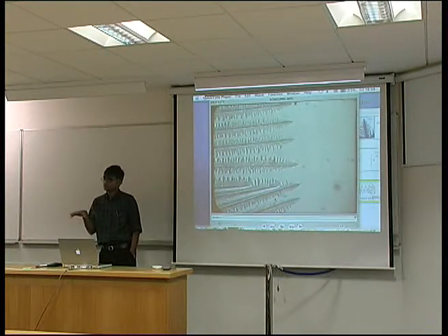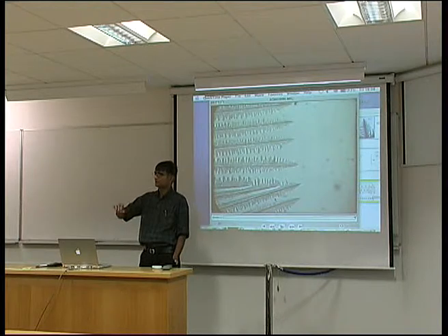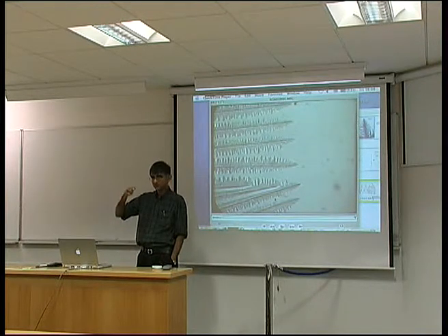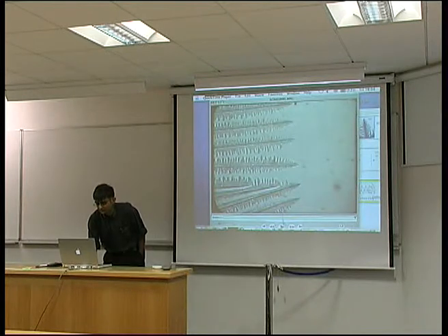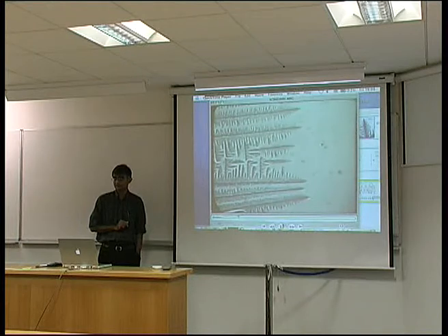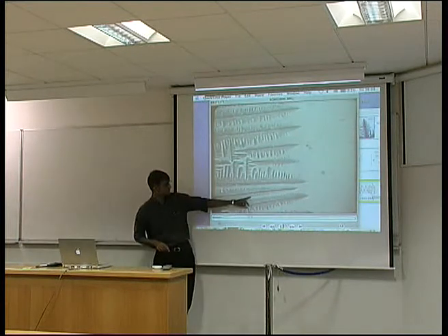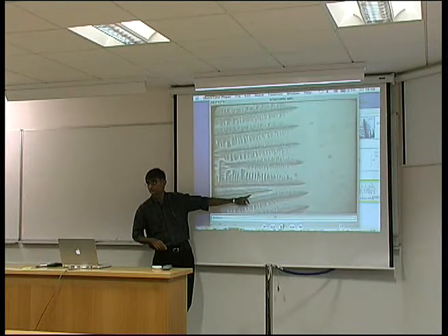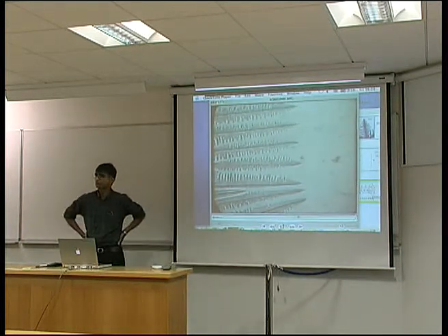So much for movies. Let me show you how good this simulation is by showing you real dendritic solidification, and you'll actually see it happening. This is a material called succinonitrile, which is transparent, so we can photograph it while it's solidifying. And you'll see exactly all those processes happening. You see the stifling of dendrites which are not growing in the optimum direction. You can see that one got cut off, okay? And there's lots and lots of branching going on.